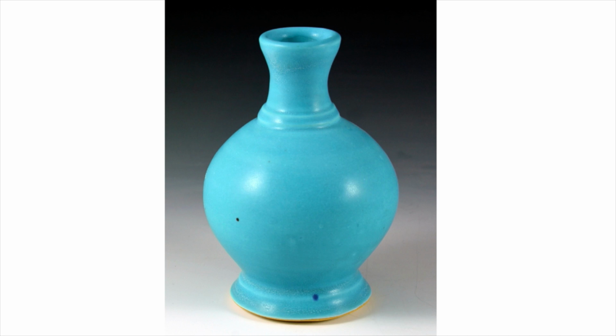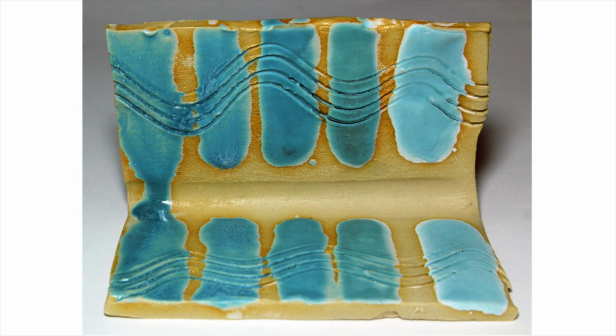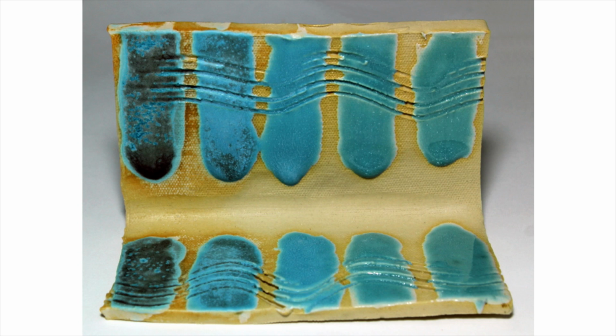Or you can take out all the clay in that same glaze recipe and add it back in 10% increments. Note how increasing amounts of EPK raise the melting temperature. Also note how the second stripe is similar to the third stripe in the previous test, making the matte glaze go from too matte to a softer matte, then satin.